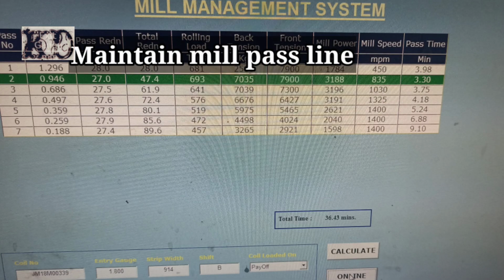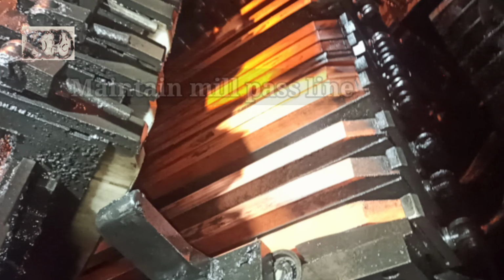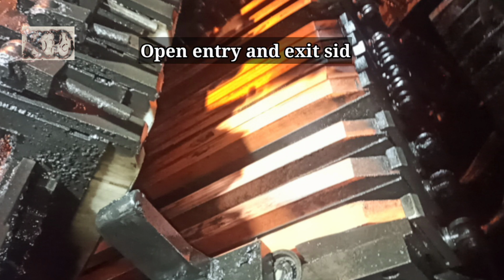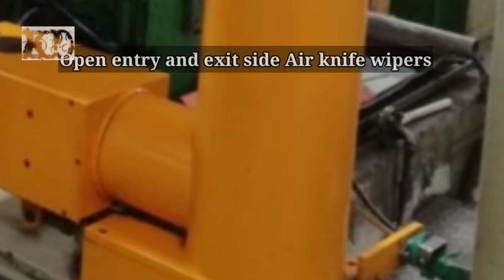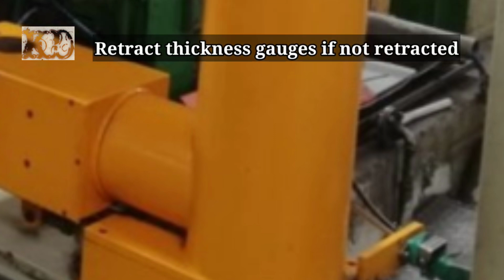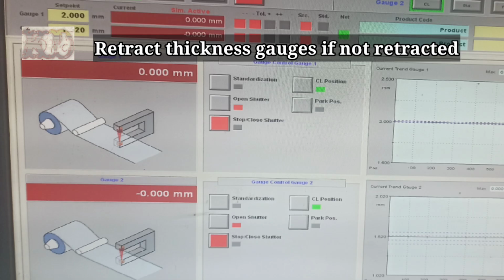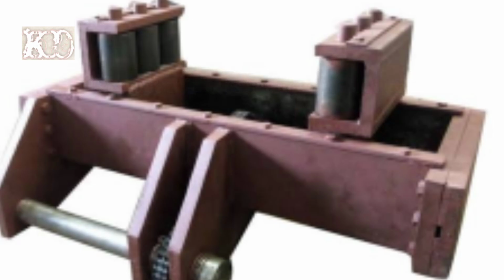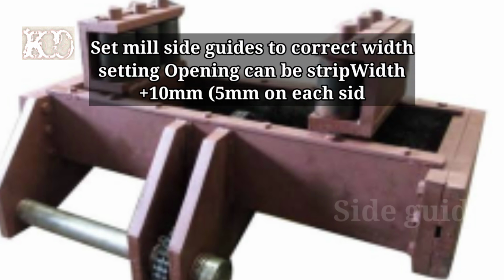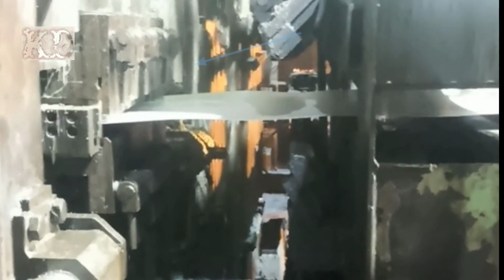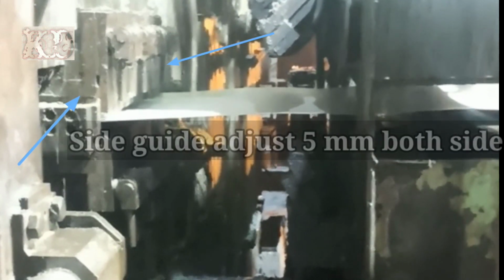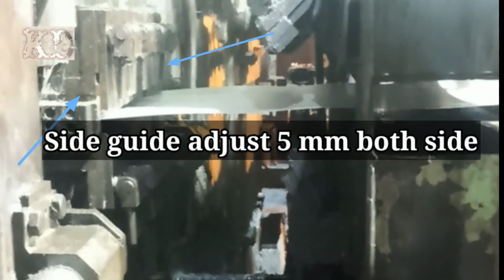Maintain mill pass line. Open entry and exit side air knife wipers. Retract thickness gauge if not retracted. Set mill side guides to the correct width settings. Opening can be the strip width plus 10 mm, 5 mm on each side.